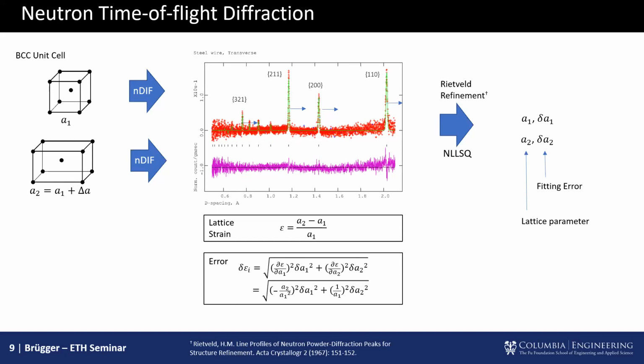Now the PSI has a neutron microscope, which goes down to 5 microns, but the field of view is essentially like 5 millimeters. And the size of the specimen you can test? The size of the specimen for the Vulcan beamline, which is a static beamline that is coming online next year, is 20 centimeters by 20. So a regular testing, and what you would do for material.